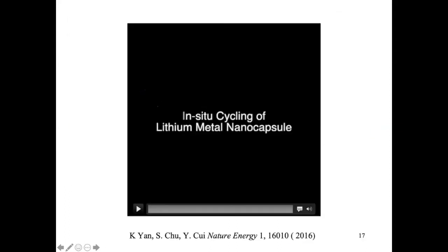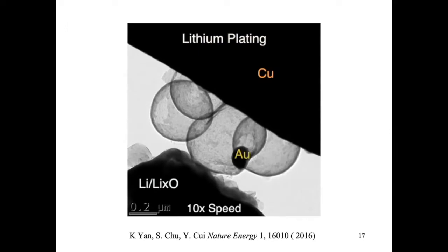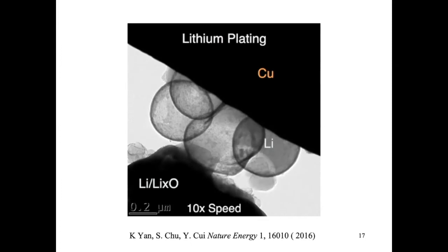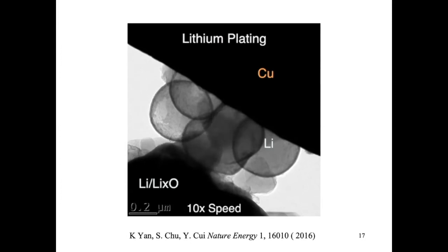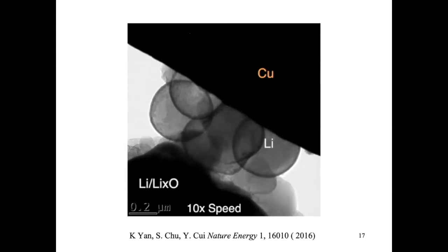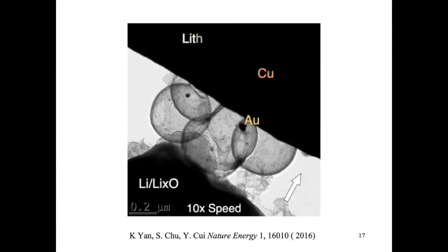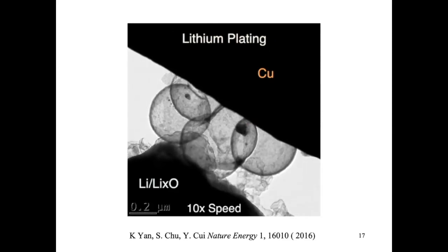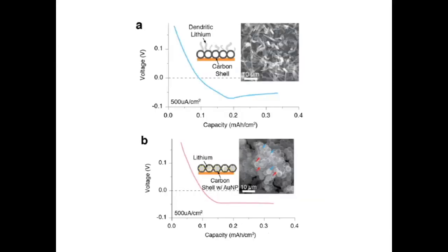And I want to show you an in situ video to indicate what happens when you do lithium deposition inside this hollow carbon with gold as seed. Once lithium is coming in, you see this gold is dissolved away. So very powerful. And lithium sits inside. Once you strip lithium out, you are going to see the gold nanoparticles coming back. So really proving our idea that the gold seed has the ability to absorb lithium and lithium can dissolve it away. That's the way to promote nucleation.